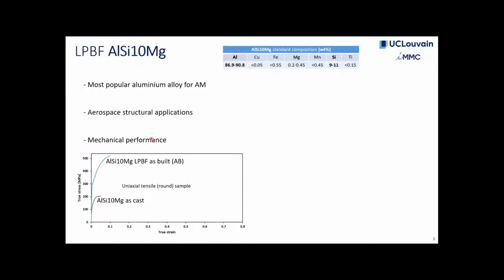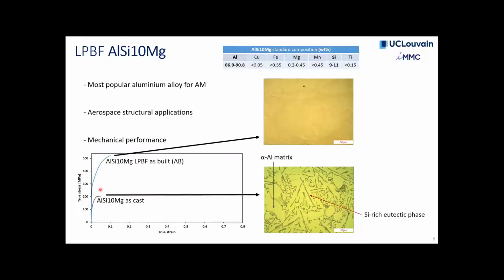this is quite critical. And in terms of mechanical properties, I just want to show you here what a cast alloy of that type looks like in terms of tensile strength, and what an aluminum silicon 10 magnesium by L-PBF looks like. And as you can see here, the strength of these L-PBF alloys is much more interesting than the cast alloys. And if you compare the microstructures of these alloys, that totally makes sense towards what we're seeing here in terms of difference in strength. The microstructure of these L-PBF alloys is very fine, while in the cast alloys, due to the difference in the cooling rates during solidification, we have a very different look in terms of the microstructure.